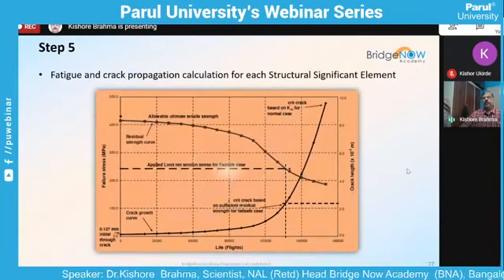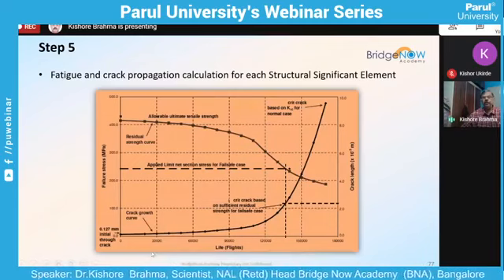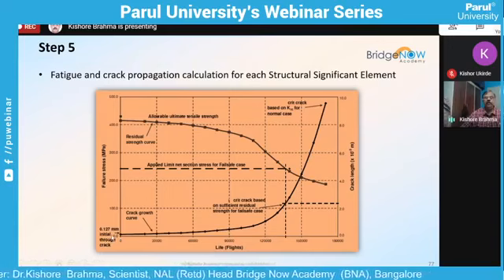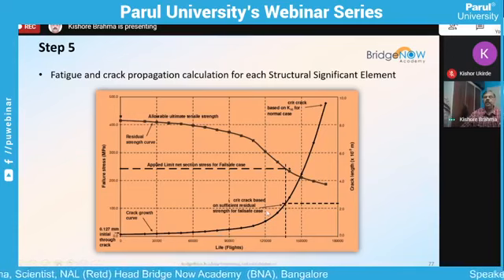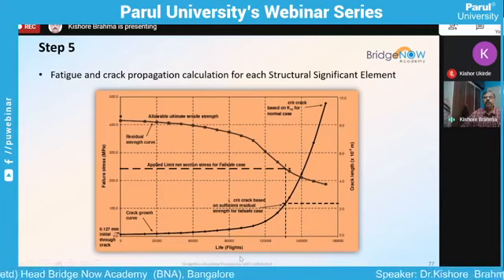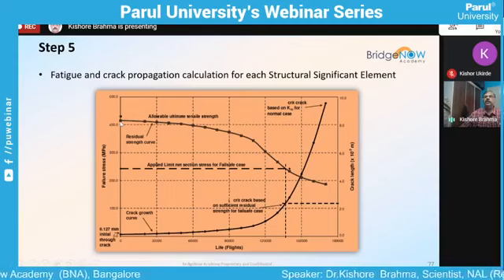See, this is a typical example done for a particular attachment. You can see that we have assumed a quality flaw of 0.127 mm. You can see how the crack grows with the number of flights. The critical crack length is coming around 9 mm if you do the crack growth analysis alone. But if you consider the residual strength of the material when the crack is 0, we have close to 400 plus, which is the ultimate strength of the material. But as the crack grows, your residual strength also decreases.